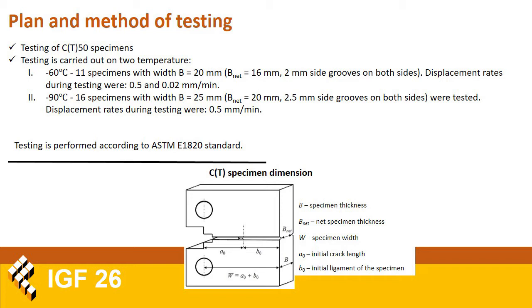16 specimens with B net 20 millimeters and 2.5 millimeter side grooves on both sides were tested at minus 90 degrees, and the displacement rate was 0.5 millimeters per minute.